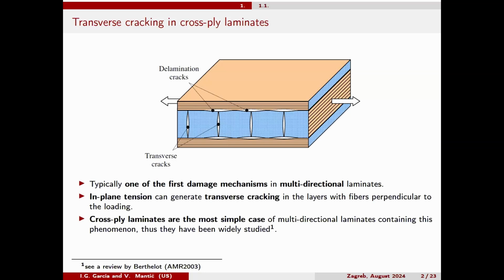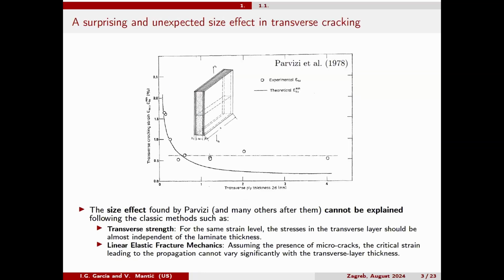In this problem of transverse cracking, the composite community has actually worked for a long time, but I would like to highlight the most surprising result. It is a result that was obtained in the 70s of the last century, so it is quite old, but it is still the subject of a lot of research that we are doing in our group, but also in other groups all over the world. This experimental result by Parvizi is actually a very simple experiment. What they did was to modify the thickness of the internal layer. So they tested different laminates with different thicknesses of the internal layer, and they tried to record at what strain level the first crack in this layer appeared.